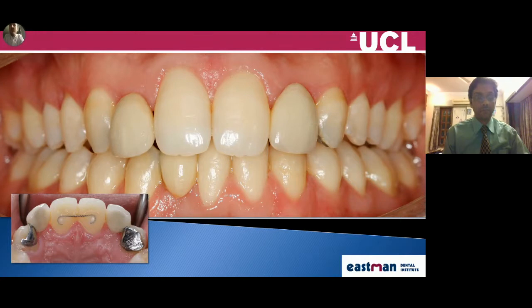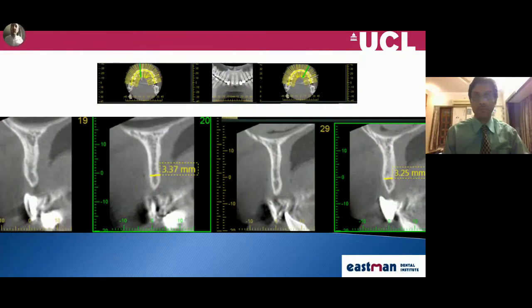The patient wanted to receive dental implants on the upper right 2 and the upper left 2 position. There was a huge defect in terms of width. We only had about 3 millimeters of bone, so we were unable to place any implants in those positions. This is very typical in cases of hypodontia. You will see that you never have enough bone to place an implant in there. In this case, we could have placed a block graft, but we wanted to try something which was, again, less invasive for the patient. So we went for the 3D titanium mesh once again.